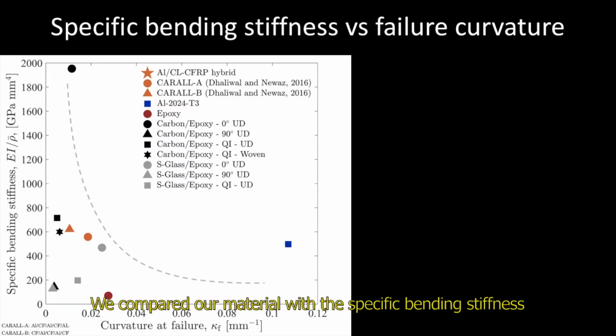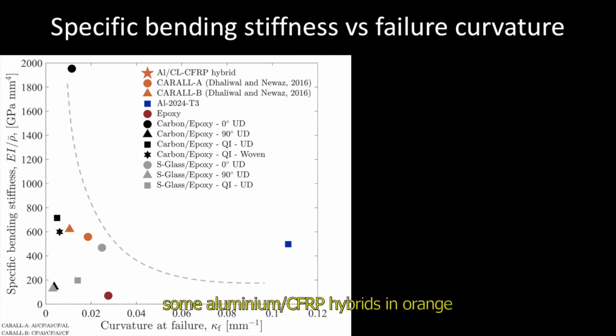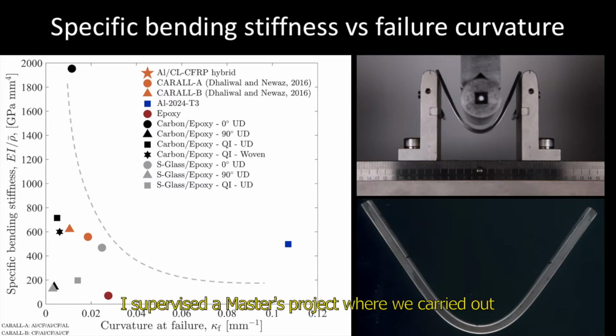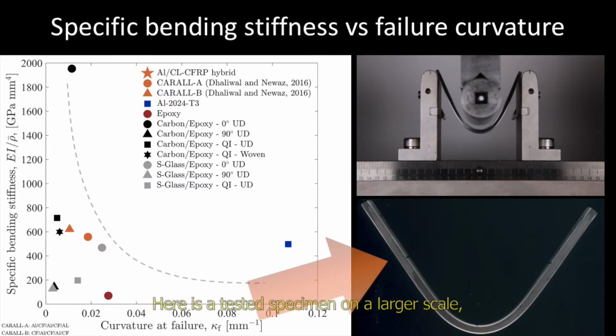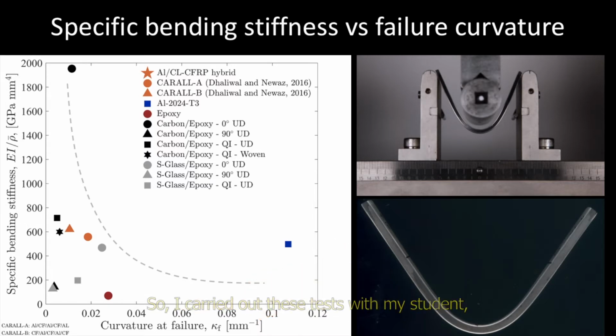We compared our material with the specific bending stiffness and curvature at failure of selected materials. Here are some CFRPs in black, glass fibers in grey, some aluminium CFRP hybrids in orange, pure epoxy in red, and aluminium in blue. I supervised a master's project where we carried out more tests on our material on macro scale. Here is a tested specimen on a larger scale, and you can see that it really undergoes large deformations without breaking. So I carried out these tests with my student, and this is where we are at the moment.